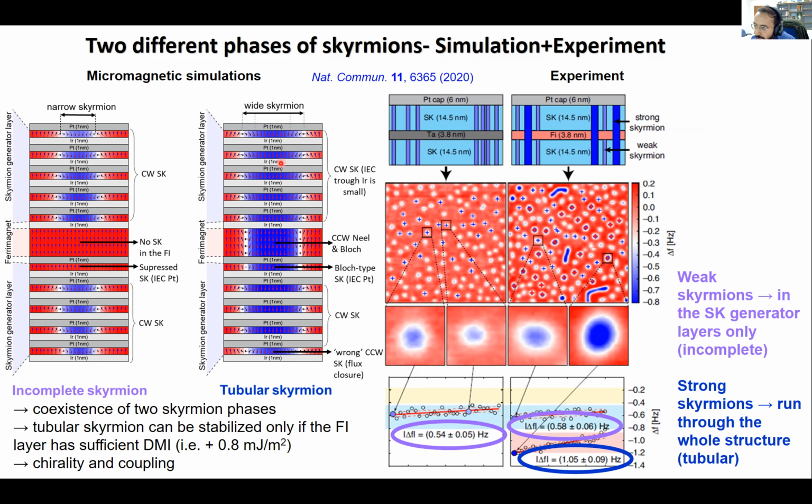So there was a continuity of the skyrmion in between the two ferromagnetic layers all throughout the ferrimagnet layer as well. Because of this, you can see that the intensity is much higher. Also, these kinds of skyrmions are wide skyrmions where it is punching through, and they are wider. The skyrmionic volume is higher, and therefore they are much brighter.